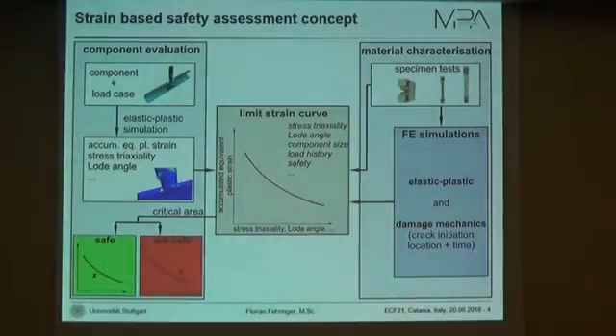Our strain-based safety assessment concept is based on such a limit strain curve, which gives us a tolerable plastic strain, accumulated equivalent plastic strain, as a function of different parameters like the stress triaxiality, Lode angle, component size, load histories, and so on. And of course, our limit strain curve must contain a safety factor. So how do we get those limit strain curves? We do a kind of material characterization, so we do some specimen tests, which on one hand directly influence our limit strain curve, and more importantly, are needed for our finite element simulations. We do 2 kinds of simulations: some simple elastic plastic simulations for things like the plastic strain or the stress triaxiality, and some damage mechanics simulations which we need for the crack initiation location and the crack initiation time.